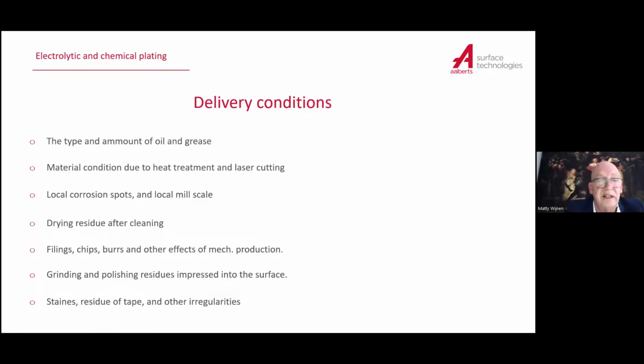Be aware of that. After cleaning, you can have drying residues. These drying residues often contain silicates, because the cleaning chemicals you use normally contain silicates. But silicates are killing for aluminum. If you have aluminum silicate, you can't remove it in your process, and you will see it afterwards all the time. Filing chips, burrs, all those things from mechanical production can give you problems, because they will be built into the coating and can break out.